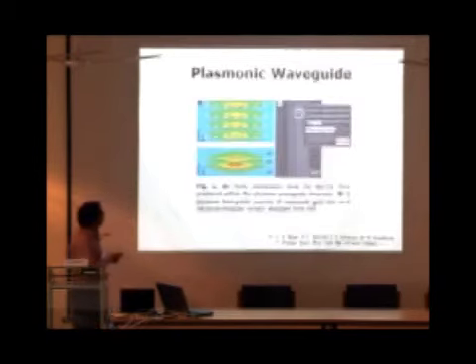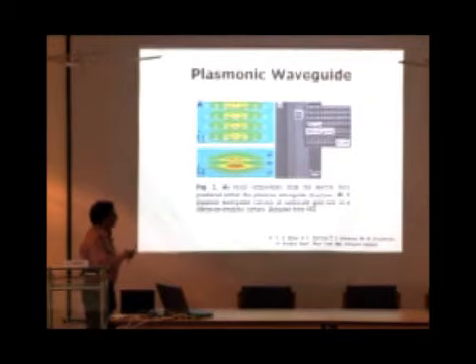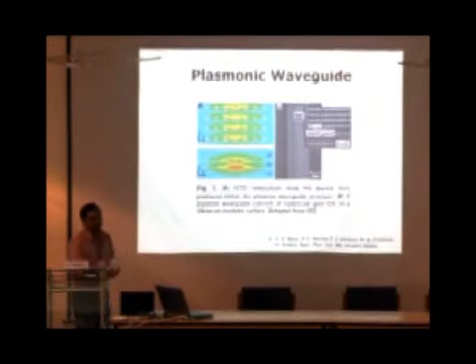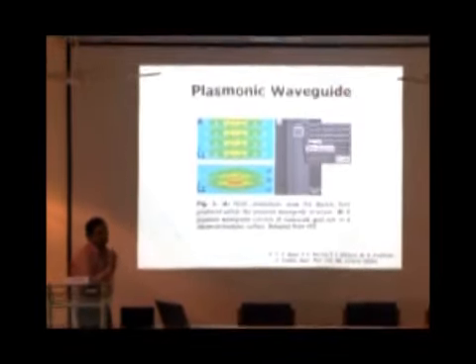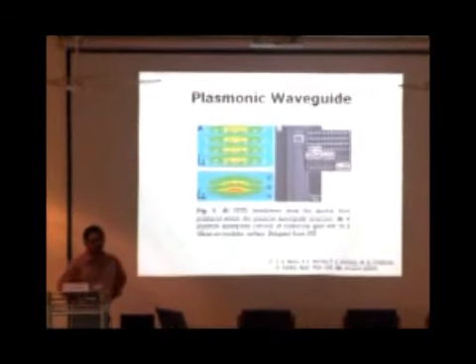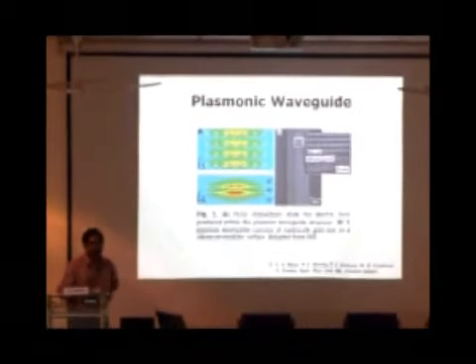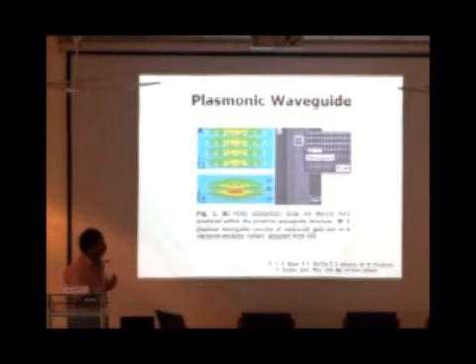So the other application is plasmonic waveguide. Essentially you can have this periodic, for example gold or silver nano dots on a semiconductor surface. So you can launch light and this acts like a waveguide for light. The advantage is again that it's sub-micron, sub-wavelength. You're talking about coupling 1.55 micron light with, say, 50 nanometer or 75 nanometer size dots.